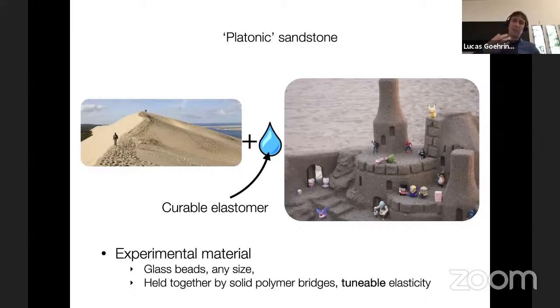The liquid goes into a ring or bridge of material between the grains of sand. And that lends the sand a bit of cohesion. And in our case, we're mimicking the same kind of materials. We have glass beads. Instead of water, we're using a liquid, which is a curable polymer. So it's something which starts out as a liquid, but when you heat it up, it will solidify. So we mix these things together. We then put it in an oven, and we have something which is like a sandcastle, but rigidly held in place by bonds between them.